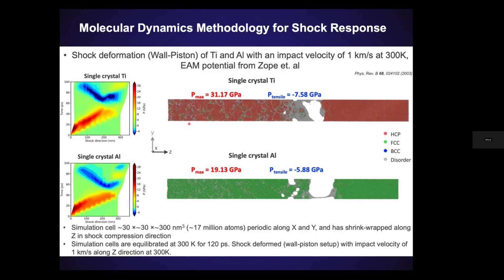You start nucleating voids. What you notice is that the stress required to nucleate voids in aluminum is about 5.8 GPa, and in titanium is 7.6. So in general, aluminum is going to have a lower spall strength as compared to titanium. That's good to know.